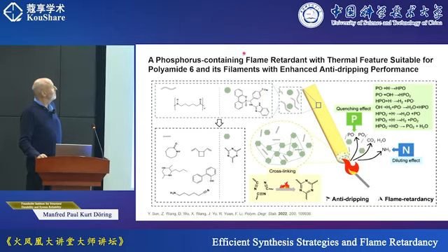They tested this flame retardant behavior in polyamide 6, and they found anti-dripping properties. And the reason for that, they postulated that reaction. That means cyanates can trimerize to form these very stable aromatic rings. And this is the reason for a higher char and the reason for this anti-dripping effect, they postulated.